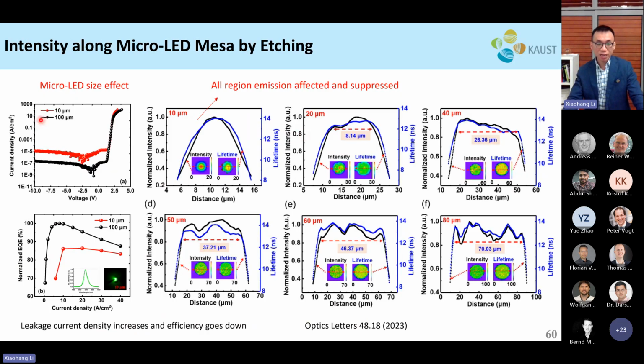So many studies before have looked at the size effect based on the plasma etching, right? When you have a very large LED pixel, the size effect is negligible because most of your light comes from the area that is away from the edge. But when you move to dimensions such as 20 and 10 micrometer in diameter, you start to notice a rapid decrease of light intensity across the mesa, right? So it has this profound reduction of the light intensity near the edge.